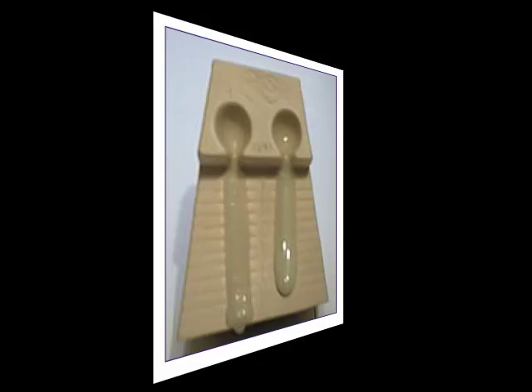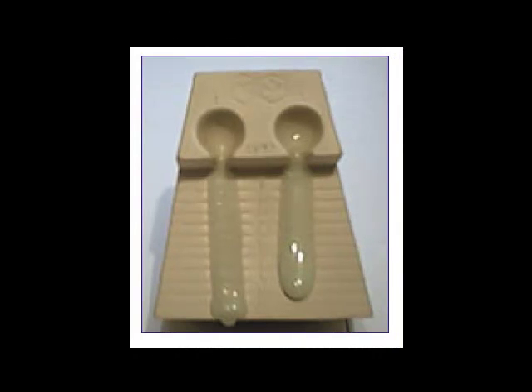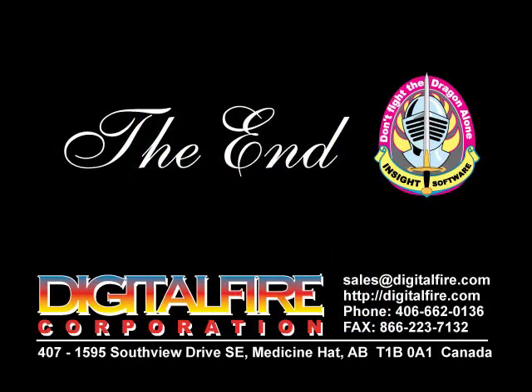Ceramic chemistry is a relative science, and it is one piece in the glaze puzzle. You cannot ignore mineralogy and physical factors like particle size, for example. These two glazes have the same calculated chemistry, but they do not melt the same, they don't have the same gloss, and one has many more entrained bubbles. However, they employ different feldspars to source sodium and potassium. That's the end of this lesson.